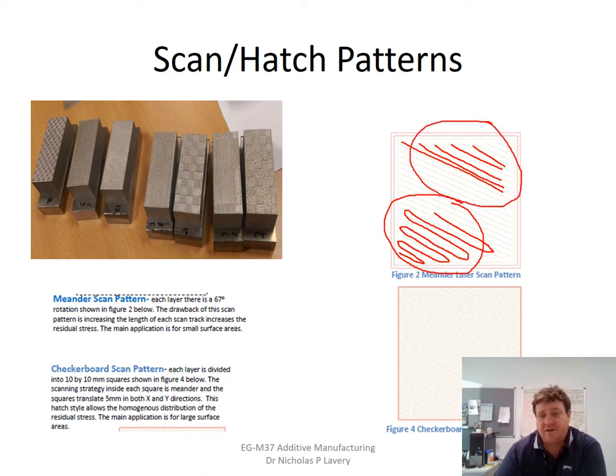Those two are the basic patterns which fill the volume area in the middle, and they can be combined into checkerboard patches, so that each of these patches can have either a meander or stripes. You can see an example here of one of the parts which has a checkerboard scan pattern, and each of those inside actually has just simple stripes moving back and forward. You can have a wide variety of different fills, and that allows you to play around a little bit with the thermal characteristics of the entire layer.